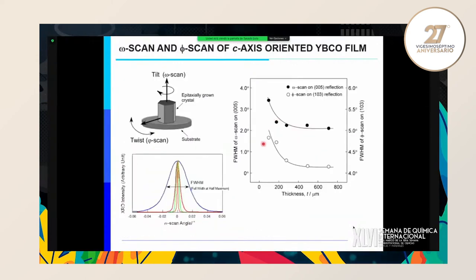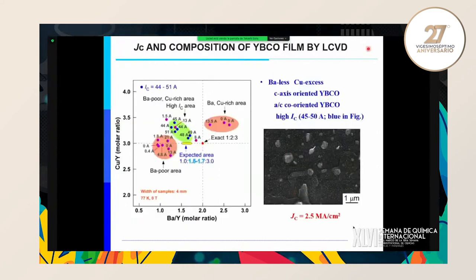Again, we have to use omega and phi scans one by one to evaluate how the YBCO grains are slanted and distorted. And distortion is related not only to temperature, pressure, and composition, but also to thickness. For example, we have to optimize the deposition condition and also the thickness of the YBCO film. So we measure the superconducting critical current. Critical current is also very important for other applications.